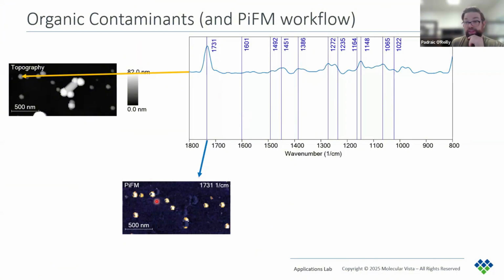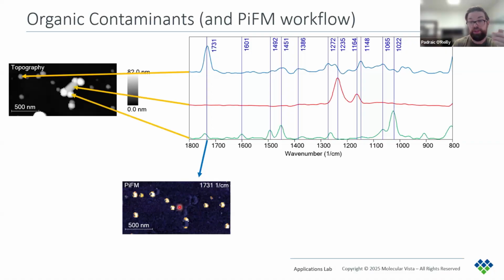And we see that about 10 of these contaminants are highlighted at this wave number. So it's safe to assume that these are the same material, but of course you could take more spectra on them just to make sure. Now we also know the particles that are dark in this image do not have this wave number, so they're a different material. Then we can go ahead and take a couple of spectra on some of these. And now we see that we have at least two additional components here. These are the red and green spectra.